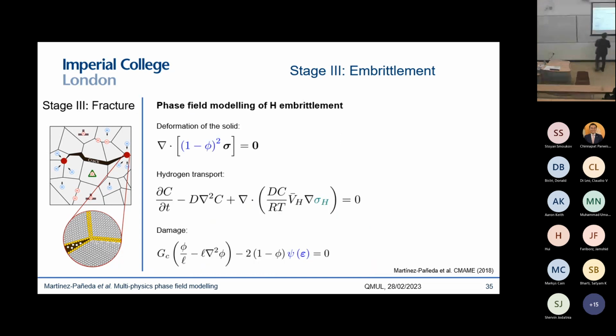So back to the hydrogen problem. Essentially, we have three equations that we're going to solve in the bulk. Once we know what the hydrogen is at the surface, that's a boundary condition for the hydrogen concentration. And then we need to figure out where the hydrogen is and when it is going to cause cracking. So I'm emphasizing the couplings here, but of course the most important coupling that I'm missing is the fact that hydrogen is affecting the damage process. And qualitatively, we know very well how to define this coupling, so we just need to make our fracture energy dependent on the hydrogen concentration. But the question is, how do you do that quantitatively?